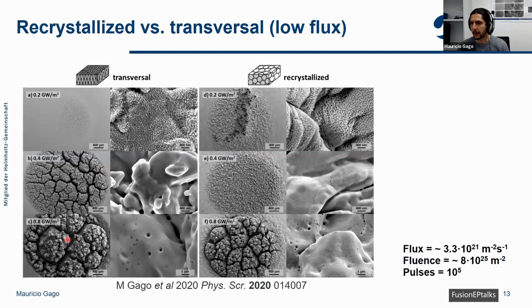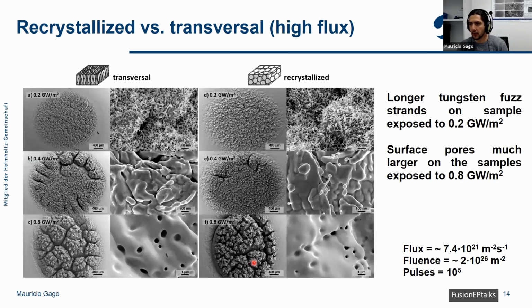And then at the highest power load, we again see that the crack network forms throughout the sample, and not only in the center, not only on the outsides of the laser spot. And this is now a more clear indication that hydrogen embrittlement, or hydrogen and helium embrittlement even, has happened. And if we increase the plasma flux, then we see some other effects taking place.